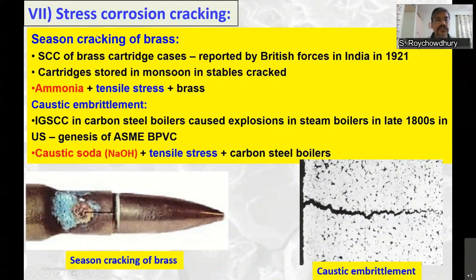reason for cracking was the availability of ammonia due to rotting of organic waste. Brass cartridges being cold drawn, they had a lot of residual stresses, tensile stresses, and brass being prone to SCC. So all these three factors led to SCC.